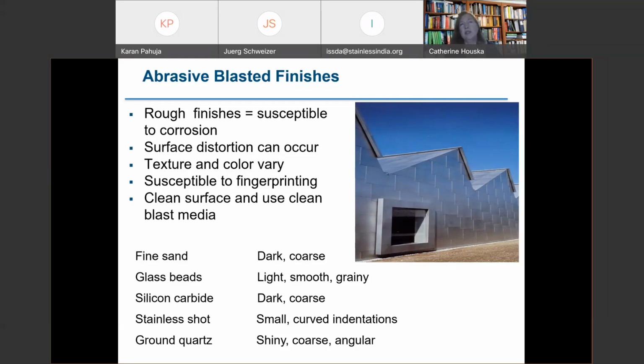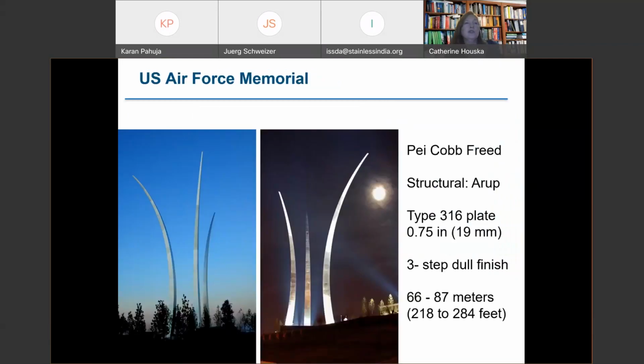This is abrasive blasted stainless steel that was used to clad a former industrial building in Switzerland, which was made into a museum. The U.S. Air Force Memorial, which used 19mm plate, is another example of abrasive blasted stainless steel. It was actually a three-step finish. The stainless steel plate was first ground to get a very consistent appearance, then abrasive blasted, and then pickled, both to dull the finish, but also to help with corrosion resistance as well.